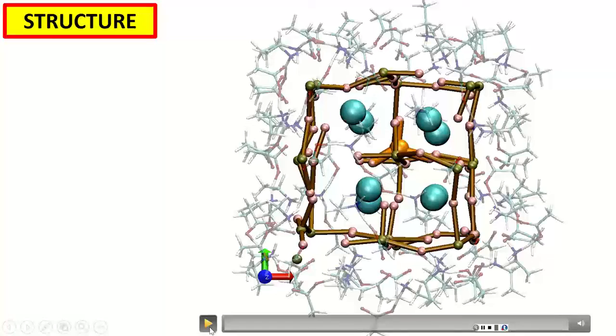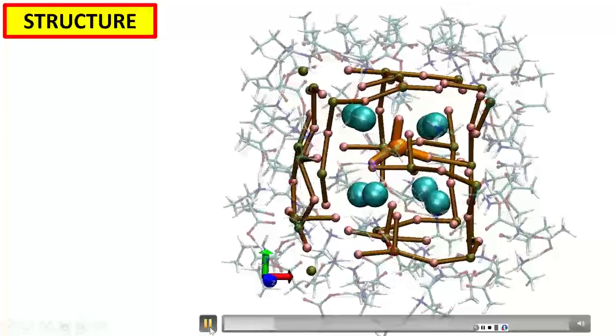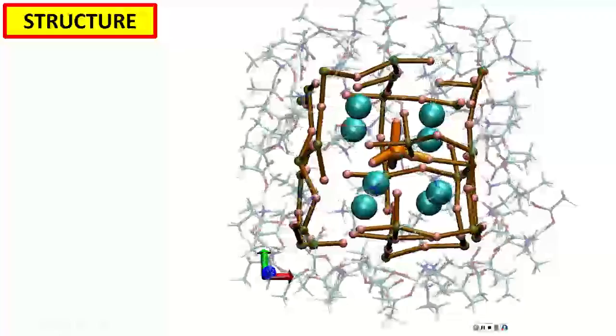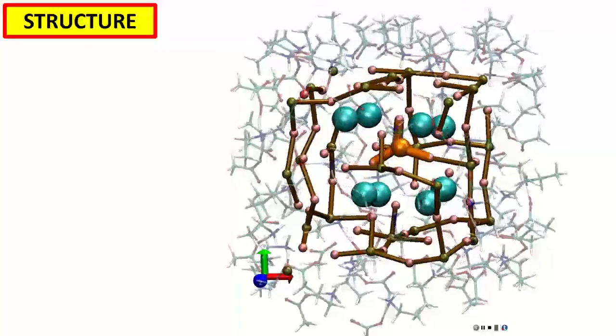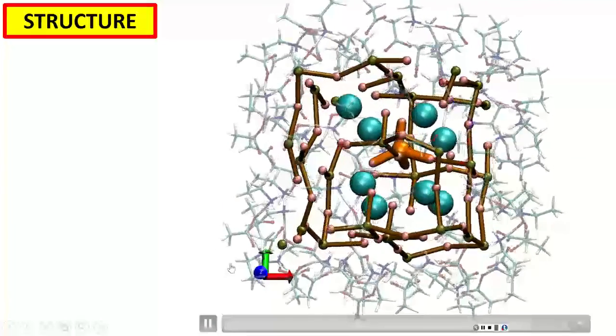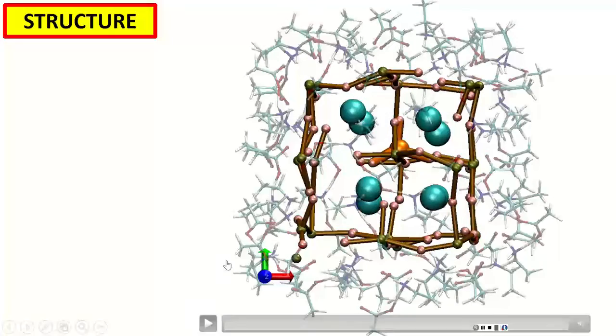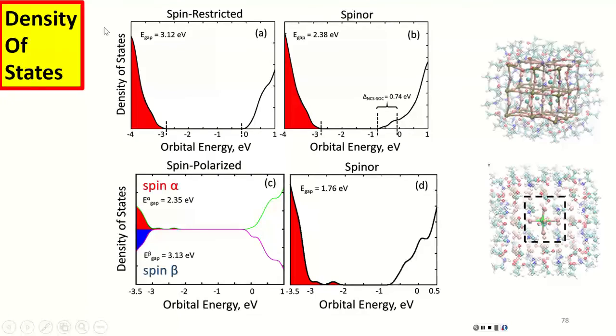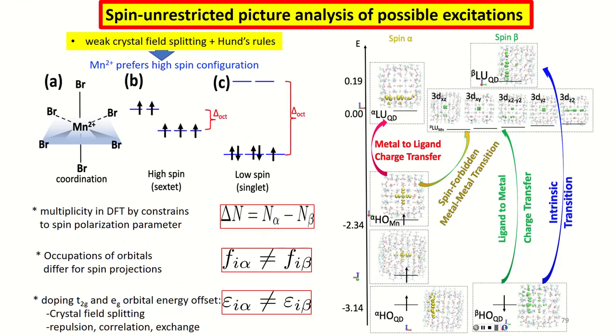Here's the structure, the scaffold of the perovskite, the semi-transparent ligands, and these blue cyan spheres are cations of cesium. Without spin orbit, the gap will be bigger. With spin orbit, it shrinks by more than half an electron volt. And if one includes spin orbit, one would allow originally forbidden transitions with a flip of spin.